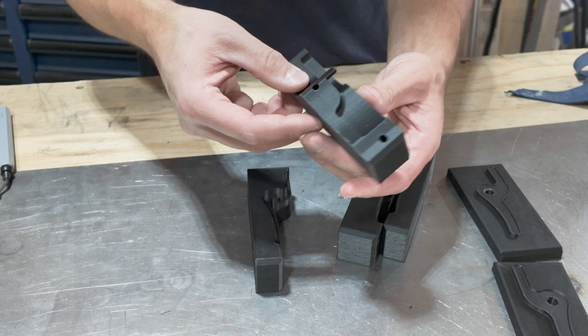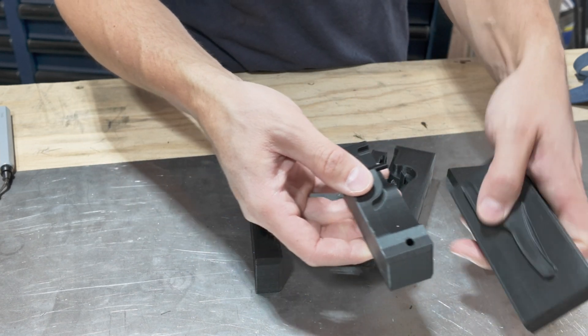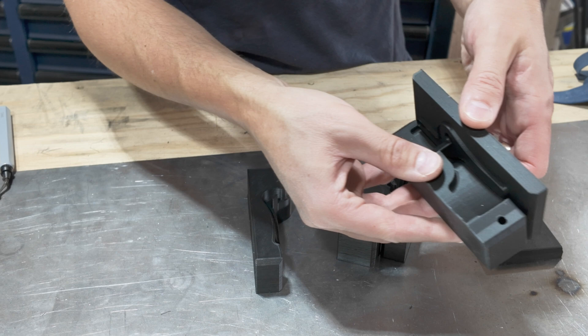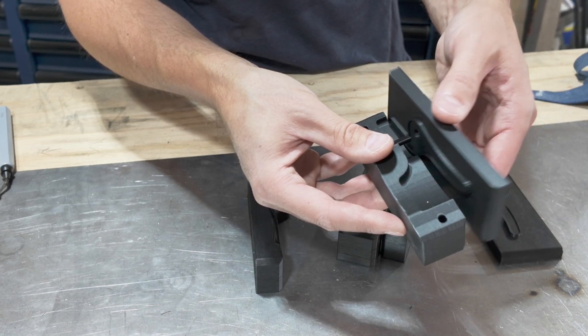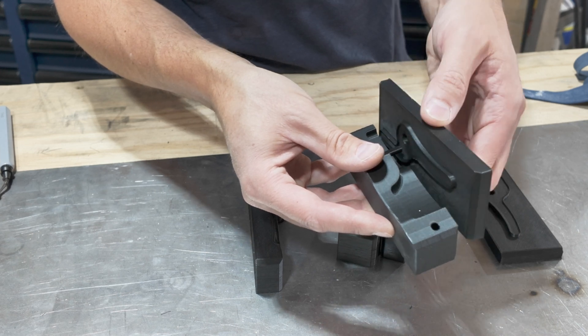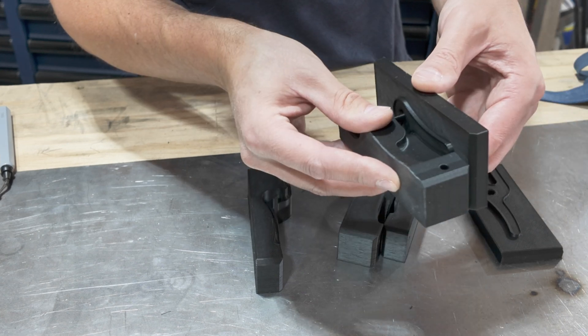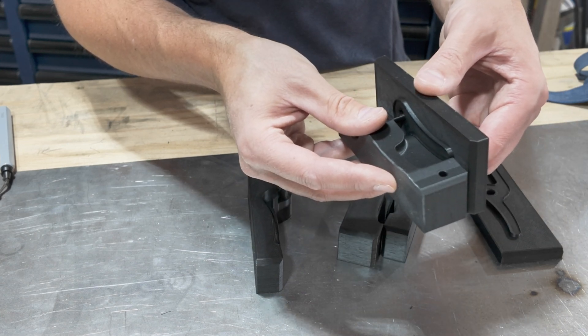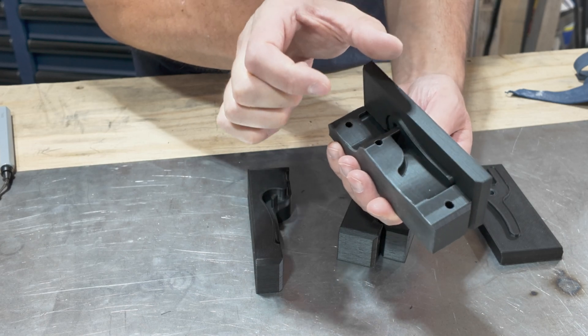I also designed this so that this part is a little bit taller than what my actual part is and the reason for that is that this piece here is going to go down. This is the piston and so once you pack that full of the carbon and the epoxy you're going to actually press this down in there. You want to press it together slowly. This will just come down just a little bit and so you can see that that will then end up putting pressure on the part and squeezing it.